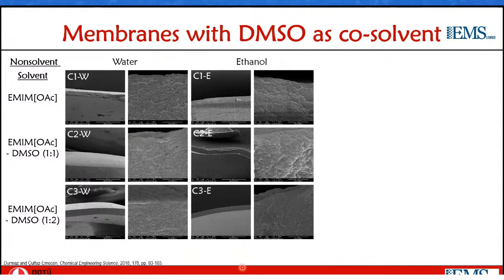In fact, for all the membranes that I've shown until now, the morphologies were more or less like this: symmetric, dense to microporous nodular morphologies. This was the same when the non-solvent used was ethanol. And then we tried adding dimethyl sulfoxide into the solvent system. It's known as a good co-solvent for cellulose in ionic liquids. And then we could, in fact, add it up to a ratio of 2:1 DMSO to EMIM acetate, where DMSO was actually the majority solvent, which is good for cost and viscosity considerations. But if you look at the membrane morphologies, they all more or less look the same.